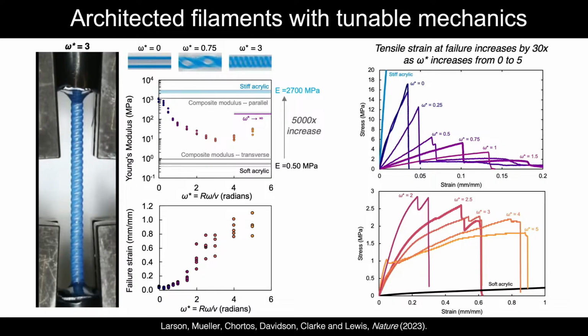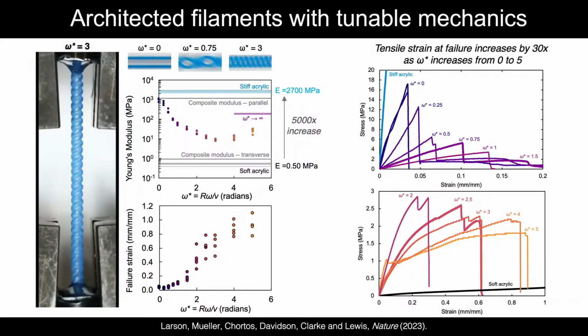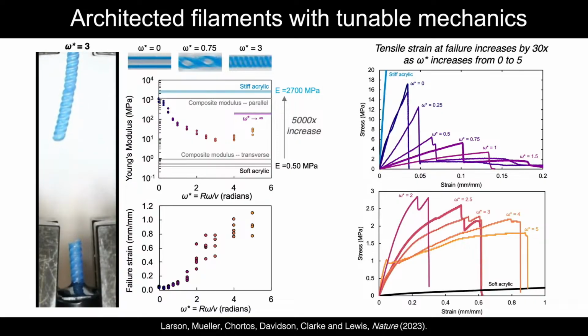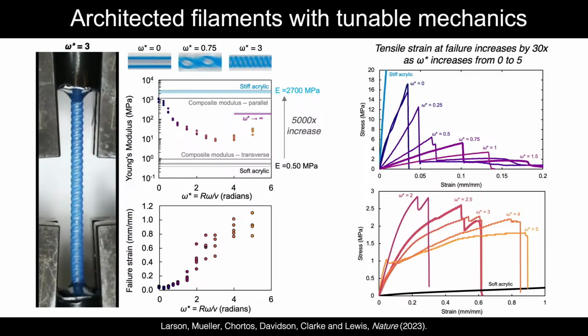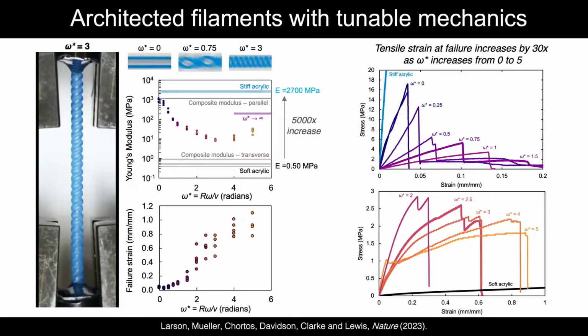Now, when we take these filaments and we put them under tension, we see that the Young's modulus as a function of the normalized rotation rate changes by roughly 3 orders of magnitude here. And we can just use simple composite theory. For example, when there's no rotation, the stiff elements are mostly the load-bearing elements, and the mechanical properties that you test are similar to the purely stiff acrylic features. And then when you're rotating at ever higher rates, you're essentially creating parallel plates, if you will, of stiff, soft, stiff, soft. And then now when you test this, you're dominated primarily by the modulus of the less stiff material.